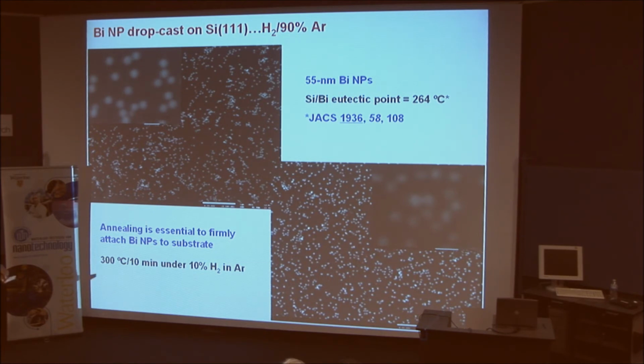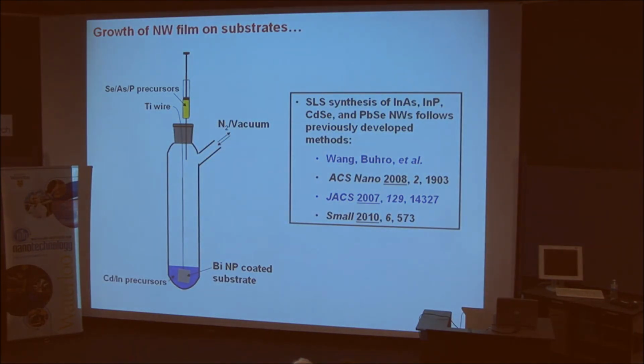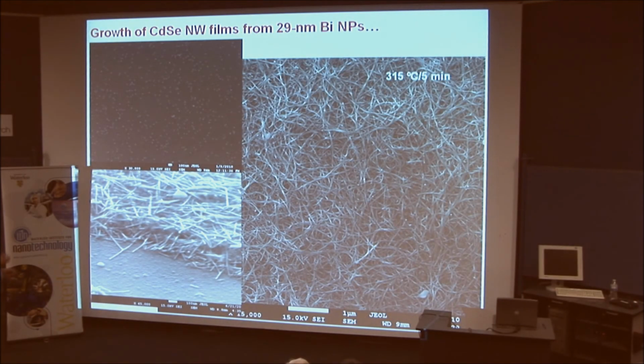If we don't do that, and we try to do a catalyzed growth reaction, the bismuth particles just float off the substrate, and we get just our normal colloidal nanowires. But this actually attaches them to the growth substrate, and then we take the growth substrate and we put it on a wire and lower it down into our reaction mixture, bring it to temperature, insert the other precursors, and we wait only a short period of time. It turns out that we can get significant wire growth in about 5 seconds using this method. And by the time we pull the films out, they look like this.